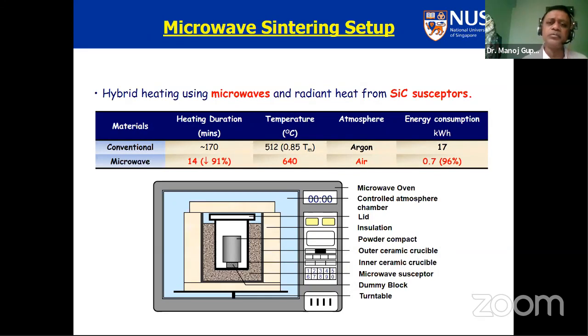The microwave that you use is the one you use at home, 900 watts or 1 kilowatt is good enough for that. Let me explain how it works. You take a microwave, you take your billet, about 35 mm in diameter, 1.5 inch roughly, and about 40 mm in height. It is placed in an inner crucible, then you have a silicon carbide susceptor, then an outside crucible, and then the reinforcement insulation to confine the temperature into this setup.